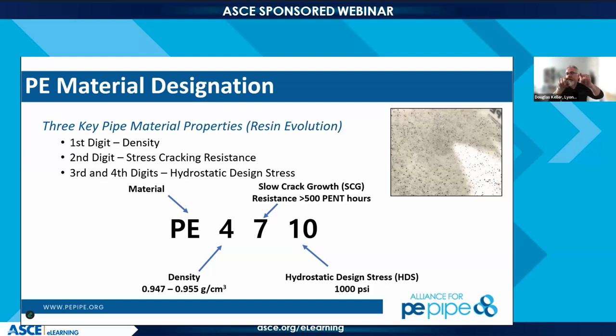So now, because we're looking at that extra time, we're now at 1,000 PSI. So when I test my material, it's actually 1,600 PSI. We then apply a 0.63 design factor that brings it down to 1,000. That 0.63 design factor basically looks at variation in my material because I don't make exactly the same thing from pellet to pellet. It looks at variation in Richard's extrusion process or any of our customers' extrusion process. And then it also takes into account typical installation issues.